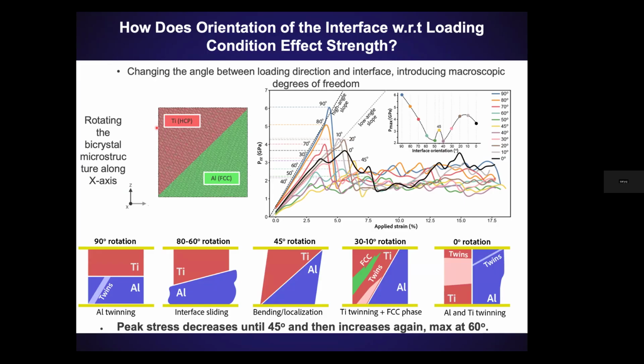So we also wanted to understand how the orientation of the interface with respect to the loading condition affects things. Let me restart that movie. Over here, you can see we rotated the interface. Remember, our loading is top to bottom. You're changing the orientation of the interface with respect to that loading condition, going from completely perpendicular to 0 degrees, or completely parallel to the loading conditions. We wanted to see: does this matter more than that interface morphology or the roughness that we were seeing?